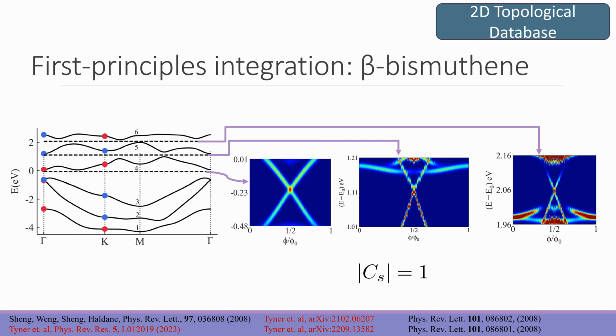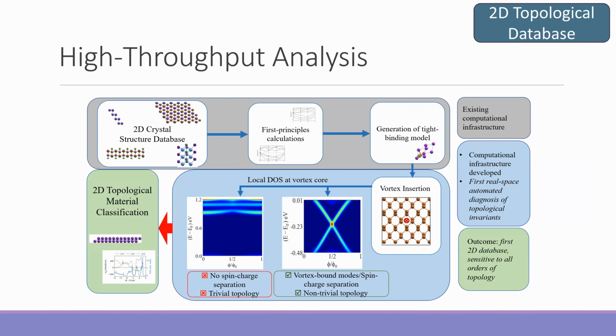So we were really excited about these results, and it motivated us to say, okay, we have a tool that we can use in realistic systems, and we know that it can look for this non-symmetry indicative topology. So armed with that information, we decided to do a high throughput real space screening. We took one of these existing 2D crystal structure databases and isolated all the systems that had been either labeled as topologically trivial or just hadn't been classified before. We removed all the systems that had been labeled as topological, because then there's no reason to do it again. And we created this workflow to do the vortex or flux tube insertion and look for these bound modes to try to say whether these systems were topological or not.